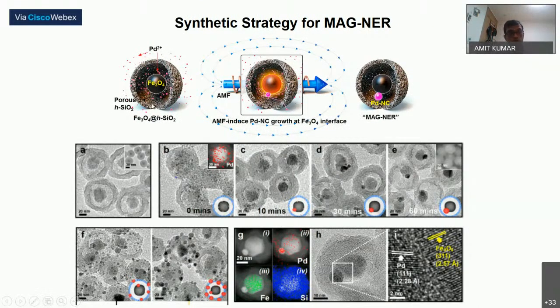So for synthesis of such a structure, we first synthesize this hollow silica which includes the Fe3O4 paramagnetic iron oxide core, and we feed this nanoreactor with the palladium precursor and apply AMF, and the AMF can locally heat this nanoparticle and actually reduce palladium precursor to generate palladium nanocrystals right on the surface of magnetic core, only inside. So in this way, we don't use any additional ligands or anything. So only ethylene glycol was used as a solvent, which is also reductant, thermally activated reducing agent.